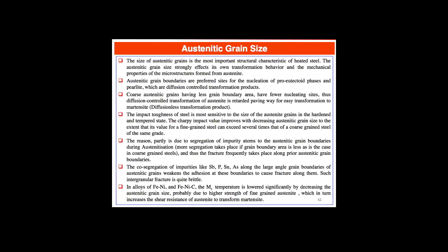And also remember, in alloying, a lot of elements will tend to segregate to the grain boundary, right? And so tin, right, is a big one, right? And so you weaken the grain boundaries, and that gives us preferential fracture paths through our material. Okay.